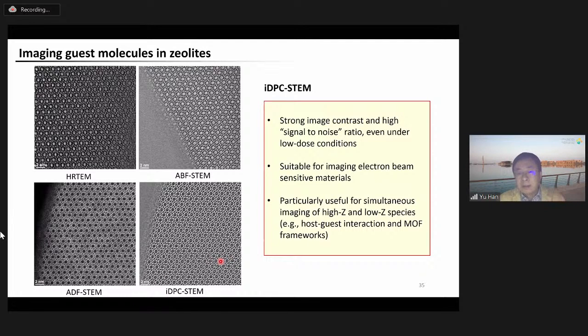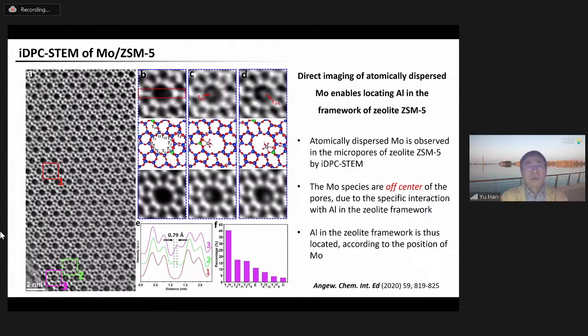heavy and light elements. And MOFs are a good example because MOFs contain both metal, which is heavy, and organic linkers, which are light elements. So iDPC has potential to be used for MOF imaging. We first applied iDPC to zeolites because zeolites are relatively stable. Actually, zeolites are also sensitive materials, but compared to MOFs, zeolites are much more stable.